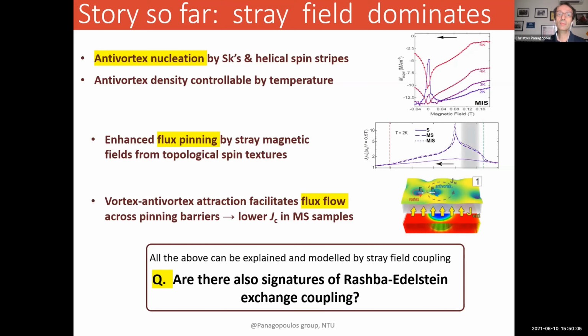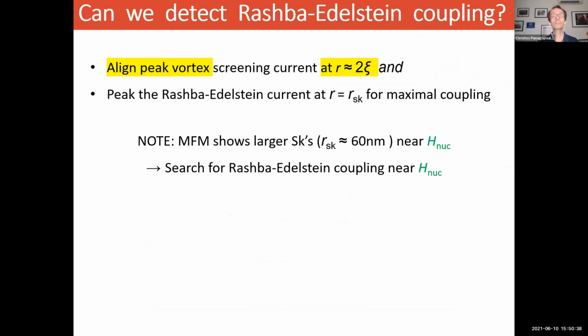And there is enhanced flux pinning by stray magnetic fields coming from your chiral textures towards your superconductor. Moreover, we were able to show that this vortex-anti-vortex attraction facilitates flux flow across pinning barriers. So all the above can be explained and modeled, as I mentioned earlier, by stray field coupling between your magnet and your superconductor. The question now arising is: are there also signatures of Rashba-Edelstein exchange coupling in this heterostructure? In other words, can we detect Rashba-Edelstein coupling in our structure or at all?